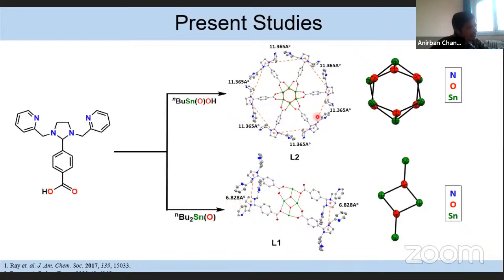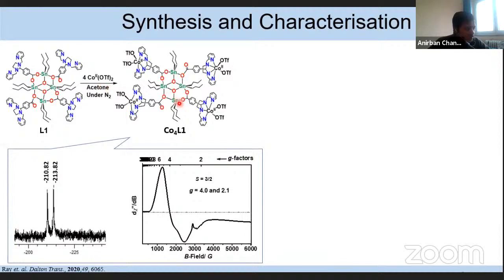These two ligands are synthesized from this ligand precursor using the stannoxane derivatives. So after getting the ligand, I did the metallation with cobalt salt, because I work with cobalt salts in my research work. So, with the reaction of cobalt triflate, this tetranuclear ligand gives this tetranuclear cobalt complex, which is characterized by the